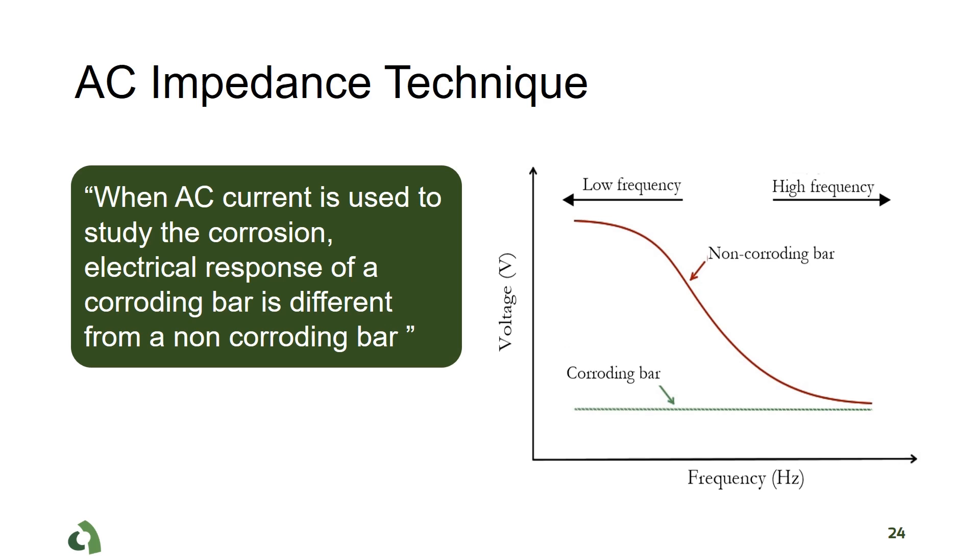The response of the system in a higher frequency range is more representative of concrete material, while a lower range is a good indicative for rebar concrete interface condition. The difference between the two can yield the polarization resistance.